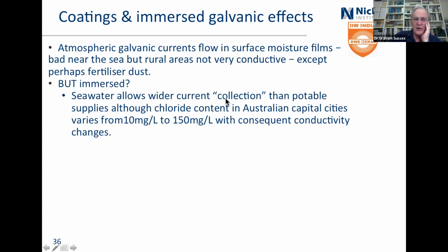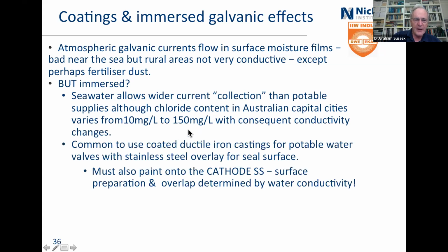If you're talking about immersed things, then seawater is going to allow wider collection, basically because it's more conductive. And if you're talking about fresh water, well, in Australia the water goes from 10 milligrams to 150 milligrams in most of the places, although Adelaide tends to go a bit worse. And it's really quite common to use coated ductile iron castings in potable water valves with a stainless steel overlay for the seal surface, because you don't really want to go closing down onto a coating.